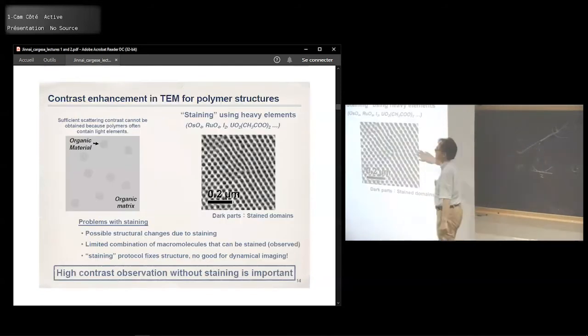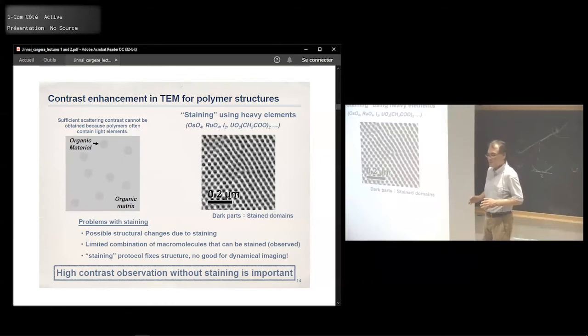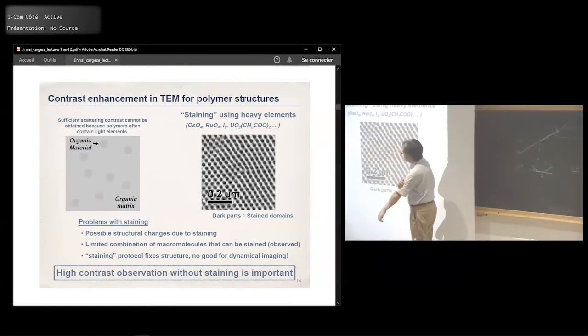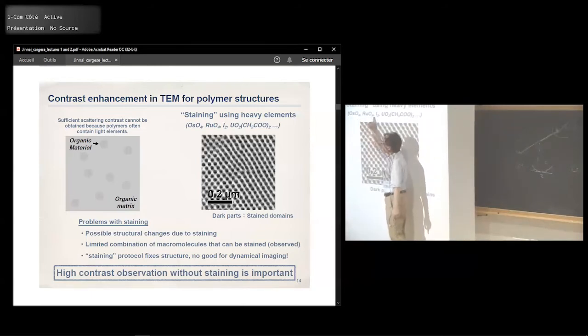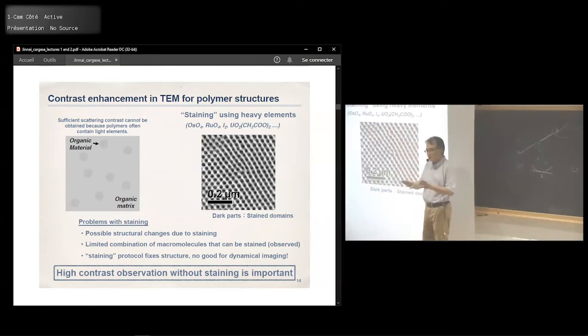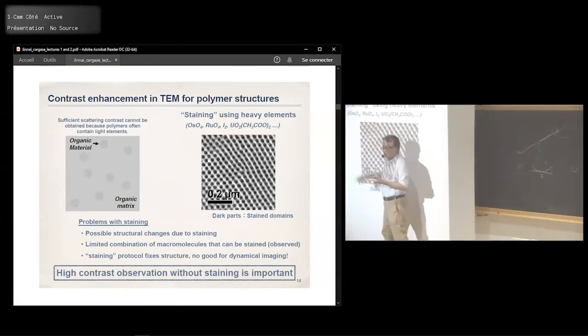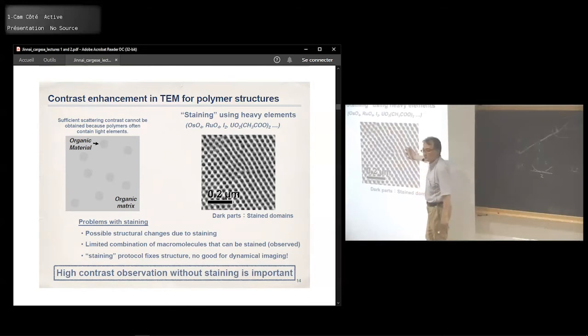Okay, this is TEM. Typically we blend the sample for a two-component sample like polystyrene and polybutadiene, and then we have a structure like this, for example. But polystyrene and polybutadiene all consist of C and H. So in terms of element, it's almost the same. So there's no contrast under the TEM. So that's why we use this staining technique, like osmium tetroxide and ruthenium tetroxide, the two representative staining agents. Osmium tetroxide stains a double bond. So if we have a blend of polybutadiene and polystyrene, then the polybutadiene, which has a double bond, is selectively stained by osmium tetroxide, and that appears darker under the TEM. Okay, so that's the staining.